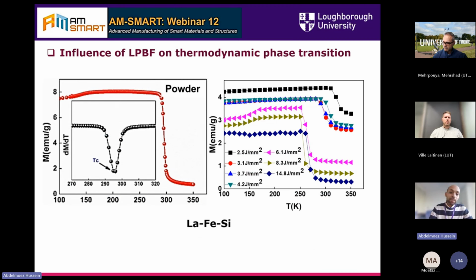So we start as normal from powder. The powder was good. It shows an almost first order transition, as we can see, like a sharp drop. However, when we process it, looking at the magnetization at room temperature, and when we process using some parameters, we can find there is a gradual transition, which is an indication of a change in the transition. Some of them give a sudden one, but we will see why later.